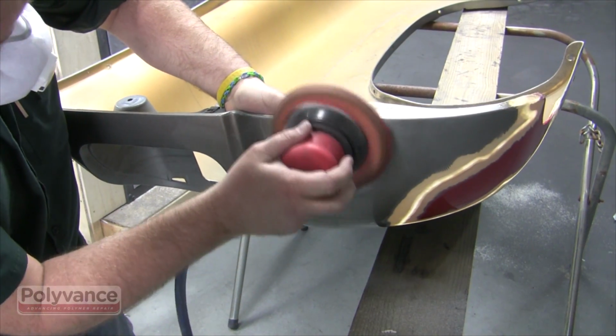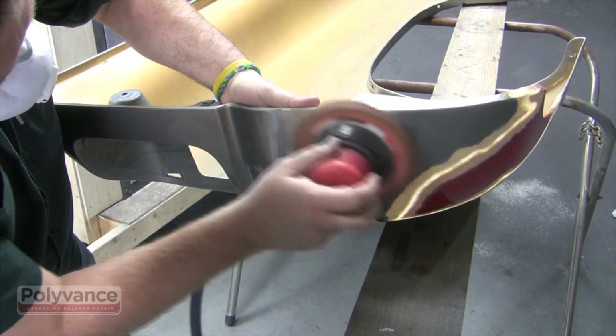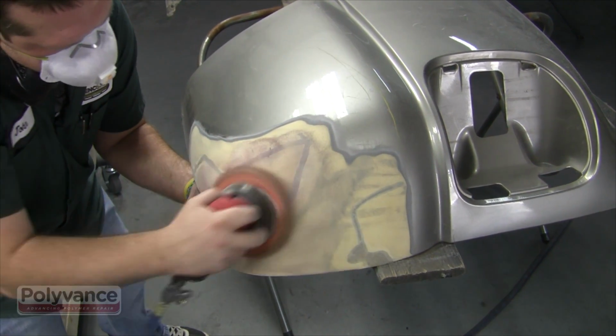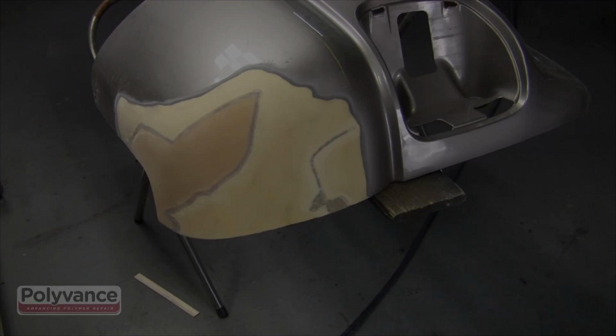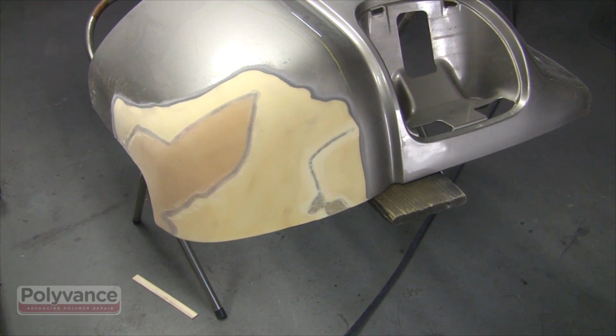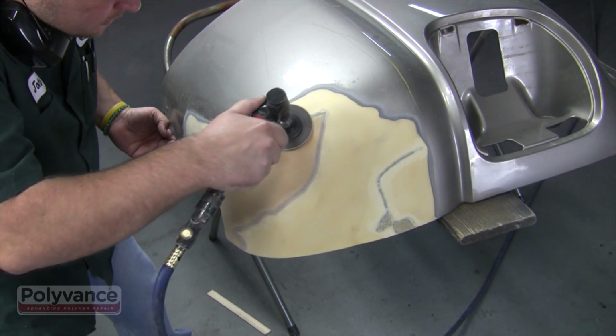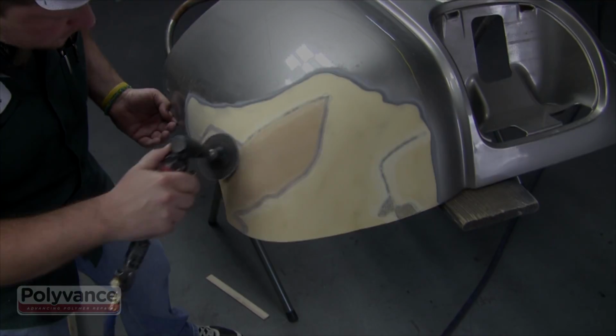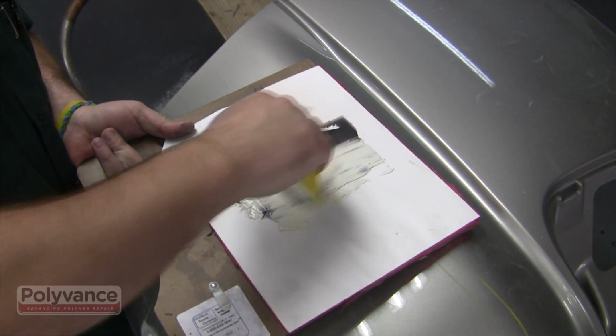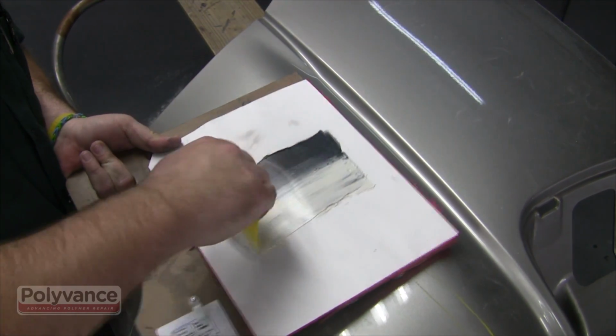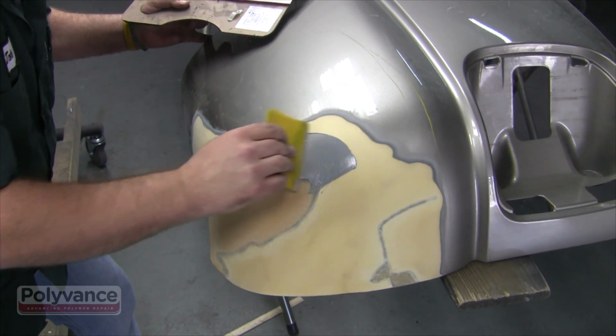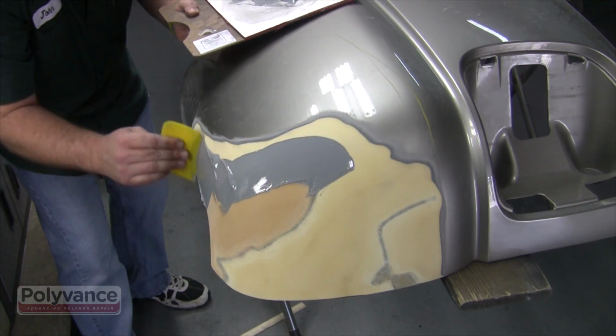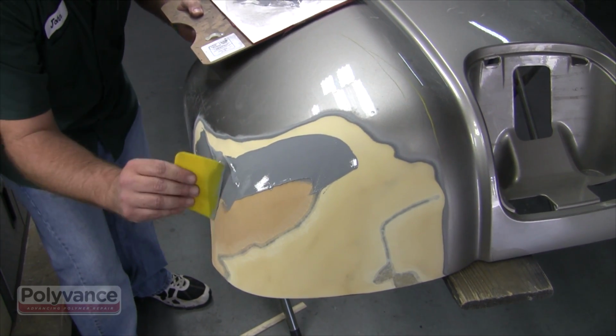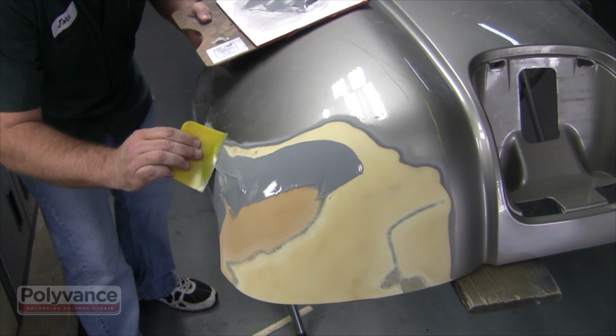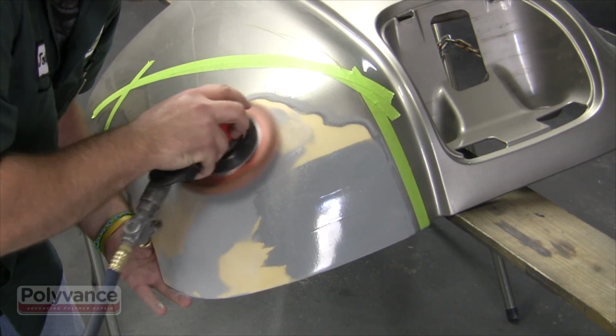Use 80 grit and a DA to feather back the V-groove and paint to prepare the plastic for filler. Mix the 2000 Flex Filler epoxy in a 1:1 ratio. Mix completely until it turns a uniform gray color. Wipe the flex filler over the welded area. Do not use polyester glazes over urethane, as they do not have the necessary flexibility.